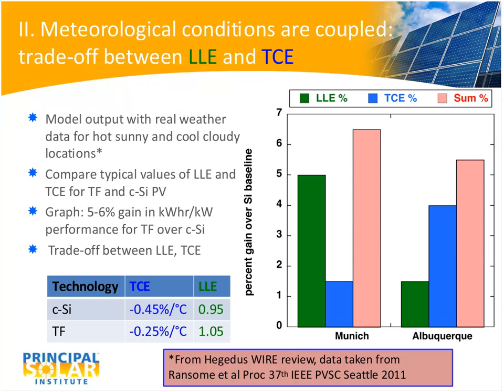This data I extracted from a paper published in a conference last year, and what it does is it compares the benefit or the gain expected for a typical thin film module that has the better temperature coefficient, namely smaller, and a better low light efficiency compared to crystalline silicon for two different locations. So the green bar is the gain in low light efficiency. So in Munich, which tends to be cloudier, the low light efficiency of the thin film module was slightly greater than 1, and the crystalline silicon module was slightly less than 1. So in Munich, the thin film module would do better primarily because of the low light efficiency, whereas the difference in temperature coefficient matters less, because it doesn't get very hot there.